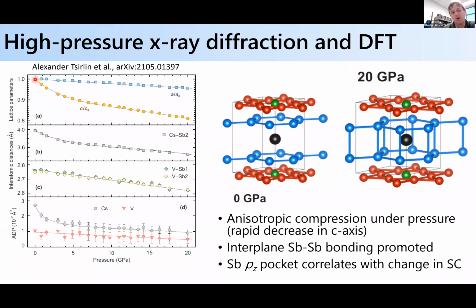This is normalized to 1, so the ambient value is 1. And so you have basically a 20% decrease in the C-axis lattice parameter by the time you hit 20 GPa. It's not sharp like the things you see in iron pnictides, like the lattice collapse phase. It's not a first order transition or something, but it is interesting that you have this really large anisotropic compression.